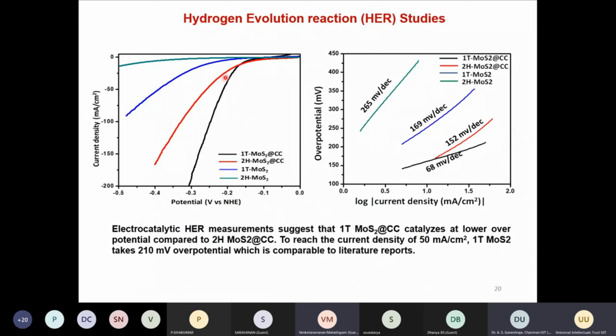And here I have shown the hydrogen evolution reaction. What we show is a simple cyclic voltammetric curve, but we have shown only the backward scan of one part of it. So here I have compared the 1T phase with the 2H phase, and as I mentioned before, platinum is the benchmark here. So what we need to do is bring this curve very close to the platinum. Here you can see that the black 1T phase shows a much lower overpotential compared to the 2H phase and the directly measured one.